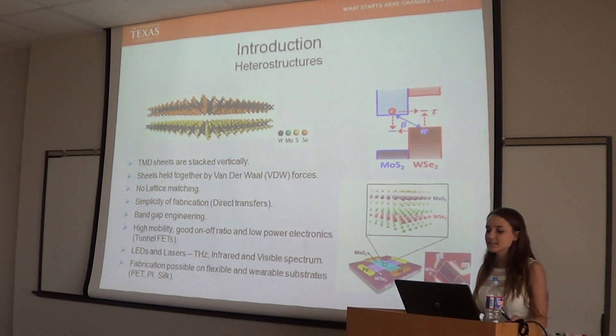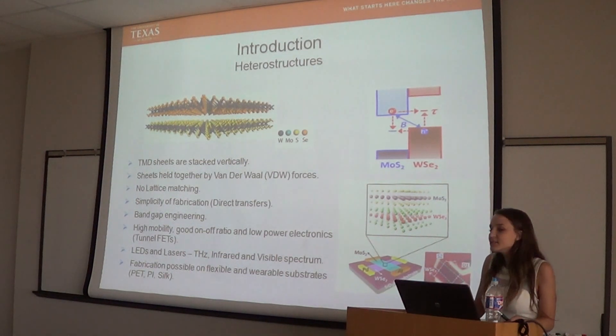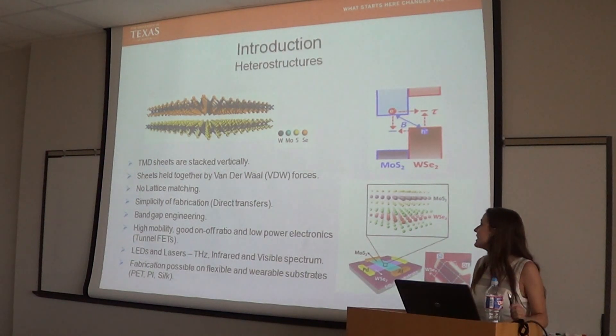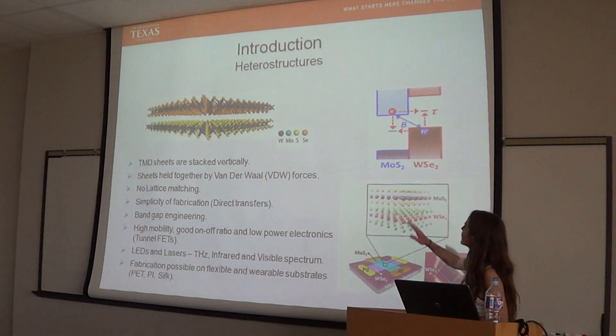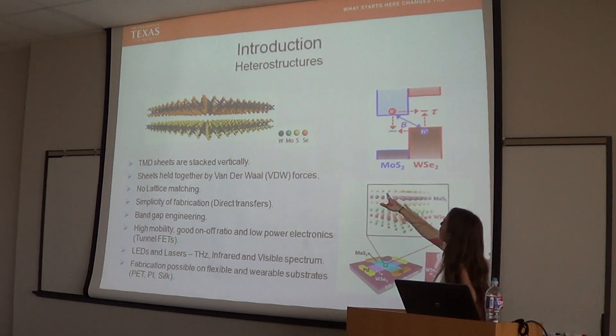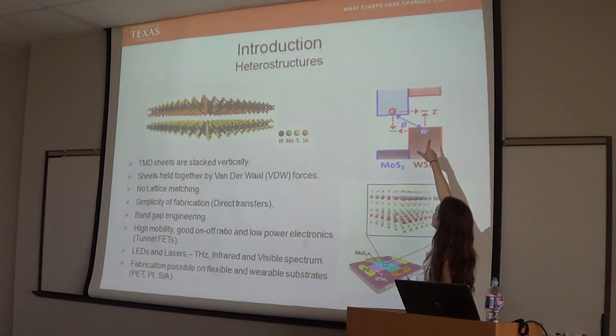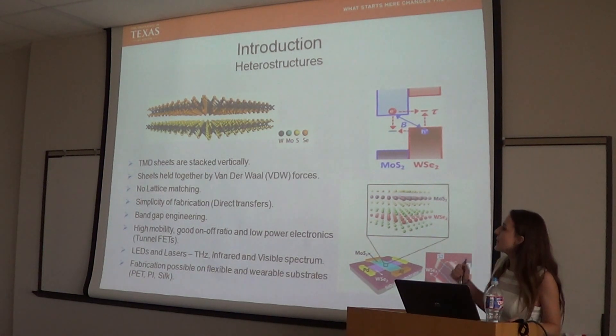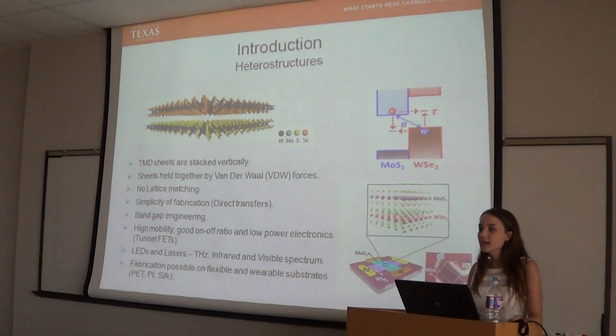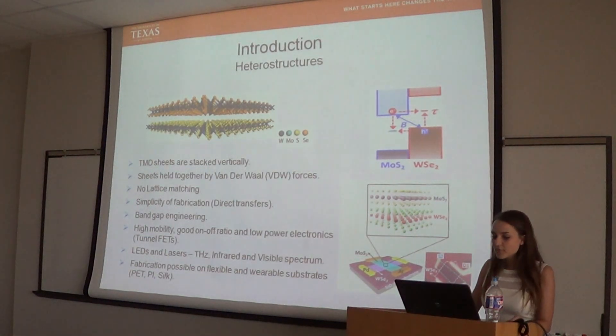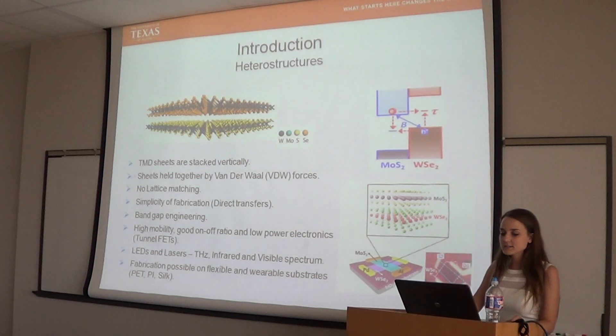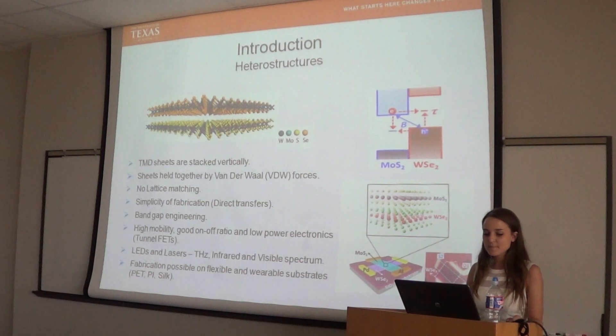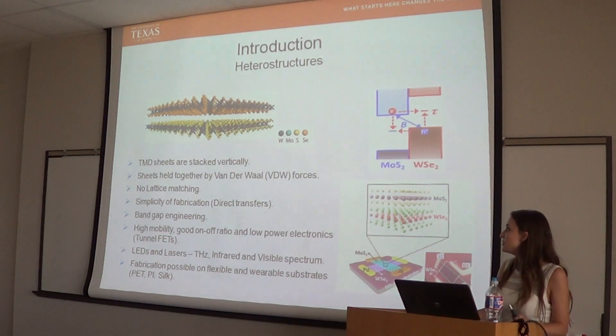Heterostructures are vertically stacked TMDs, held together by van der Waals forces, which means they're simple to fabricate — there's no lattice matching. You can see here we have a MoS2 and a WSe2 flake. This is the band gap for MoS2 and this is the band gap for WSe2. When you create your heterostructure, you actually create a new band gap, which we're able to manipulate to create high mobility, a better on-off ratio, and lower power electronics. You can even create LEDs and lasers in terahertz, infrared, and visible spectrum.